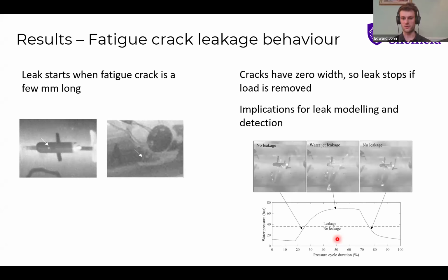However, water loss only occurs when you have some kind of load to hold that crack open, when these cracks are very small. So these cracks have zero width before any kind of corrosion can occur over a longer period of time to basically widen the width of the crack. So what that means is, unless the load that caused the crack to form is present, the crack will close and water can't escape.